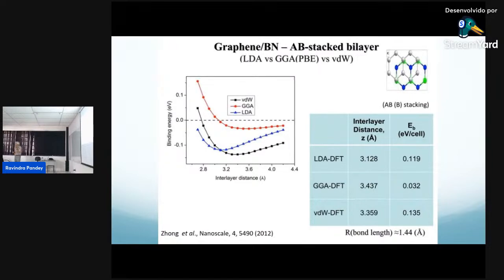This is a slide for the people who do the modeling. This gives you an idea about the functional forms. So we have, as you know, LDA, GGA, and vdW. So this is a very, very approximate form. And you can see here, the binding of this bilayer system is almost invisible as you improve the accuracy. So you have to go really very, very high in the accurate sort of Hamiltonian, which improves the so-called van der Waals interaction. This sort of shows.